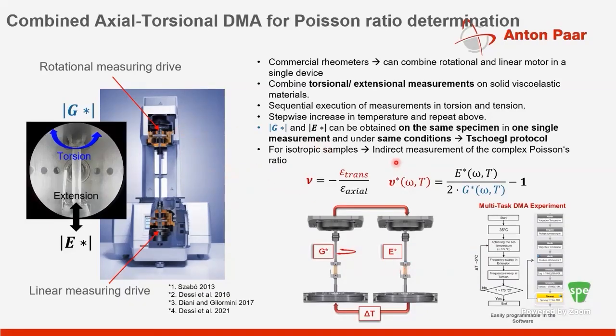And for isotropic samples, you can then use this E and G, at least for an isotropic sample in an infinitesimally small strain limit, to define the Poisson ratio as shown here.